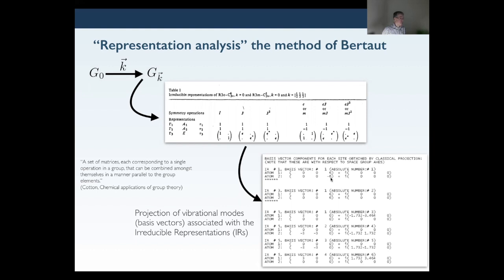So these are the space group axes, the unit cell axes, rather than being in Cartesian. We have A, B, and C components. The C components here are the same size, but they're plus and minus. So this would correspond to an antiferromagnetic relationship between those C components.